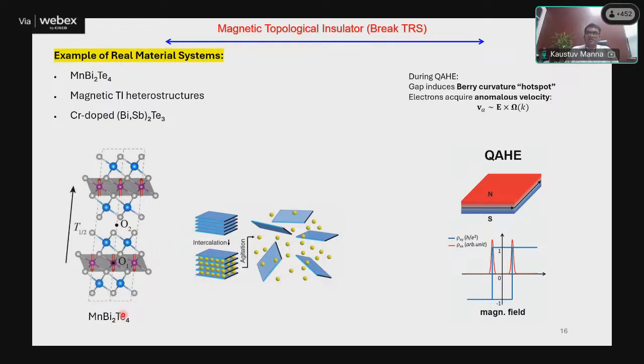This is a natural grown single crystal with layer by layer magnetism, as well as, in between, bismuth telluride, Bi2Te3. It is the topological insulator. And you can think of MnTe, bismuth telluride, again MnTe, again bismuth telluride. So it is like a naturally grown layered compound, bismuth telluride in between two magnetic layers of MnTe. These MnTe layers, because of their exchange interaction, are antiferromagnetically aligned. That is the ground state magnetic property of this compound.